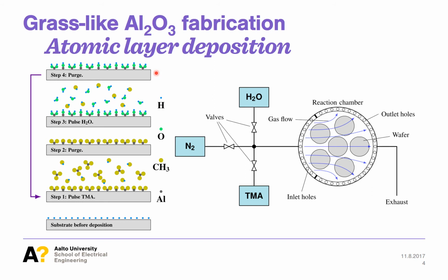Self-saturated surface reactions of ALD enable conformal growth of structures with extreme topography, as no other thin film growth technique can match. In addition, ALD is not a line-of-sight growth technique, as the precursors are delivered in vapor phase and react only with the surface. This enables batch growth of hundreds of components at a time if implemented on an industrial scale.